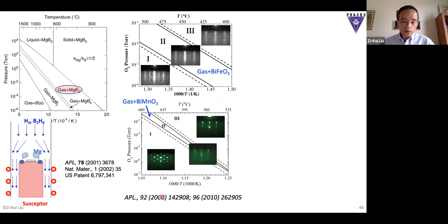We work with Darrell Schlom's group, and they do experiments, very nice, very beautiful experiments, beautiful diffraction patterns, and then we do the calculation there. Of course, calculations always have uncertainties. The dashed line sort of gives the uncertainty range. But this uncertainty is still big enough, right? The window is still big, but this one is very big. This fluctuation will reduce the window by half. So it was very, very interesting work. We made it, that's a very nice one.